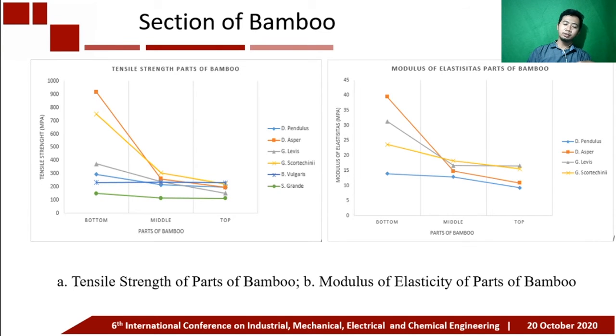Okay, section of bamboo. Next parameter, the section. This graph shows the highest tensile strength and tensile modulus at the bottom of the bamboo. The strength decreases at the top of the bamboo. This applies across all different types of bamboo. So for using bamboo as a composite fiber, it is recommended to use the bottom.